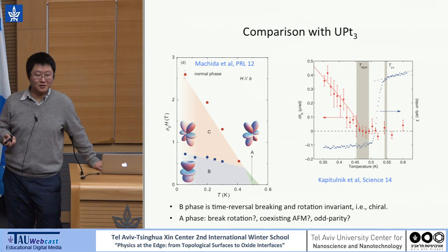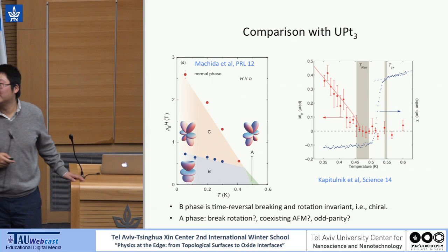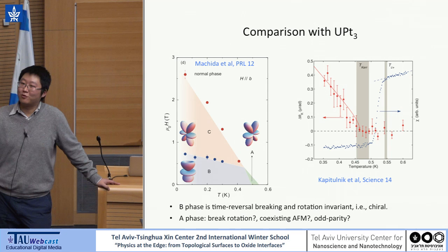So this is why I think this nematic state is actually much easier to detect than, for example, pinning down the d-wave nature of cuprates, right? In that case, you really require phase-sensitive measurements. But here, the magnitude of the gap itself is already anisotropic.